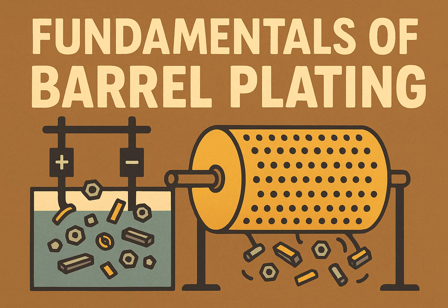Then there's roughness or burr on the plated surface. This usually indicates solid particles in the plating solution. Like dirt in the paint. Exactly. This could be dirt, particles generated at the anodes, impurities precipitating out of the solution due to high pH, or contaminants from the makeup water. Filtration of the plating bath is the primary solution here, along with careful control of pH and current density.